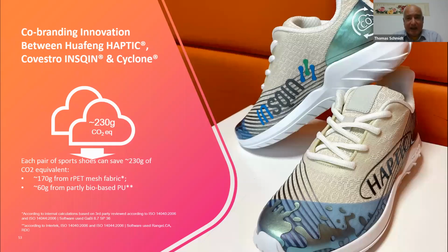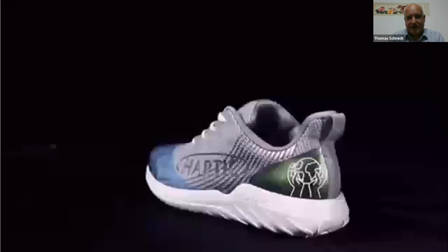And at the end, we calculated the CO2 savings for one pair of shoes is about 230 grams per pair, which is, in our opinion, a significant contribution. When you look into more detail, you find out that out of these 230 grams, about 170 grams of CO2 savings come from the recycled PET mesh, and about 60 grams come from the haptic partly bio-based printing ink. So the summary of our project here is really a significant lower CO2 footprint.